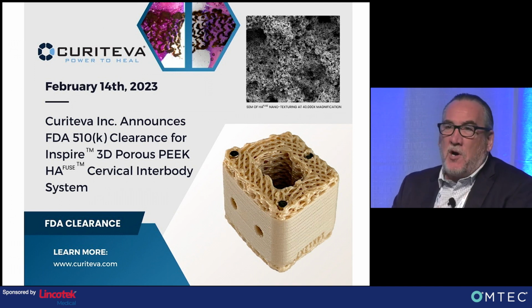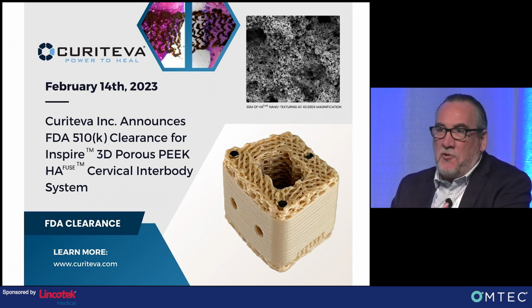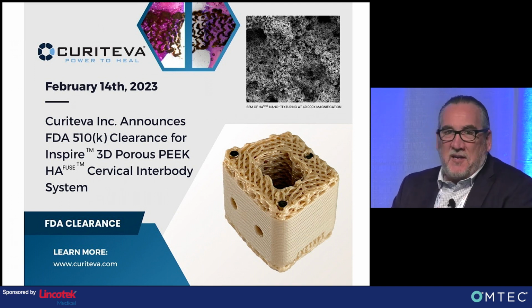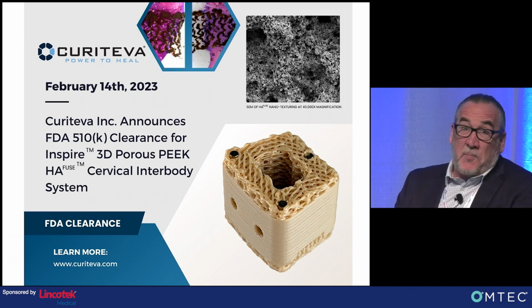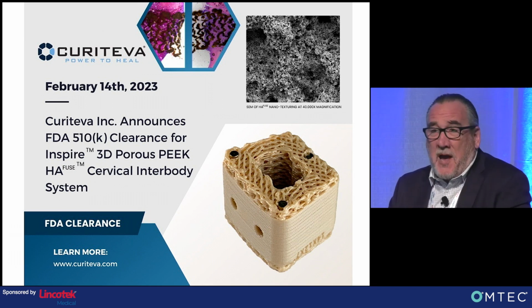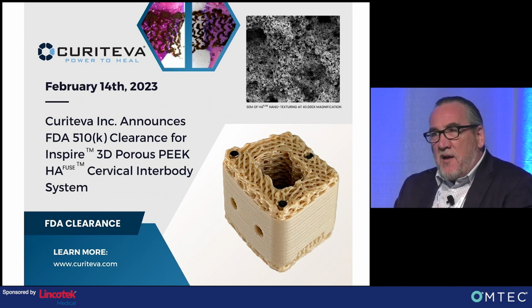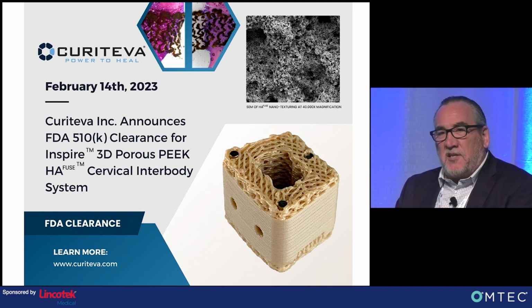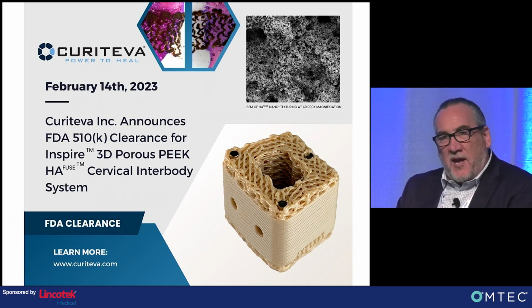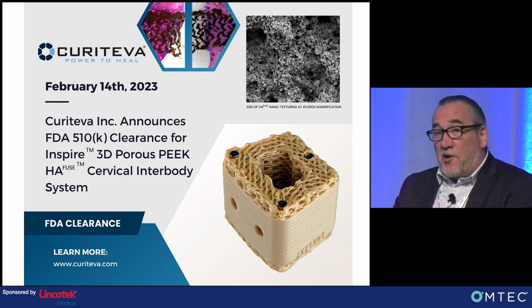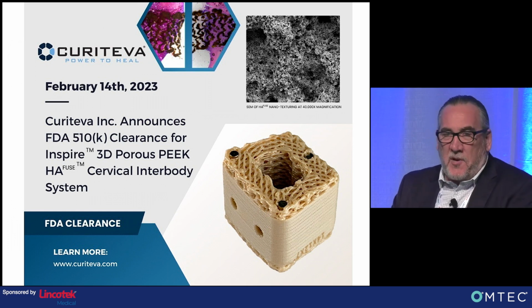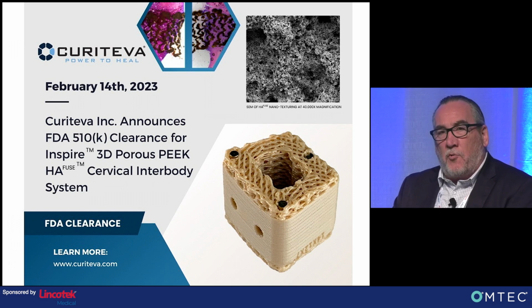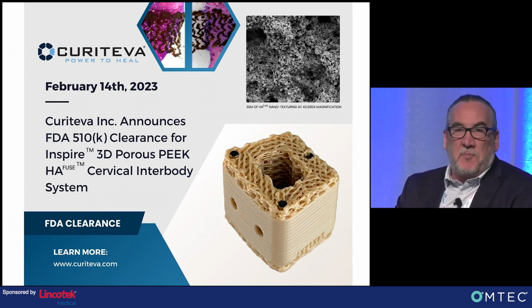It took 18 months to get the clearance, and as most of you know, a typical 510K is 90 days, especially on a PEEK implant. It should happen very quickly. But FDA wanted to really understand the process and the impact on the final properties. We were very confident that we could meet all the ASTM standards, but during that process of sharing information with FDA and getting them comfortable with this process, we did a lot of tests that went above and beyond.